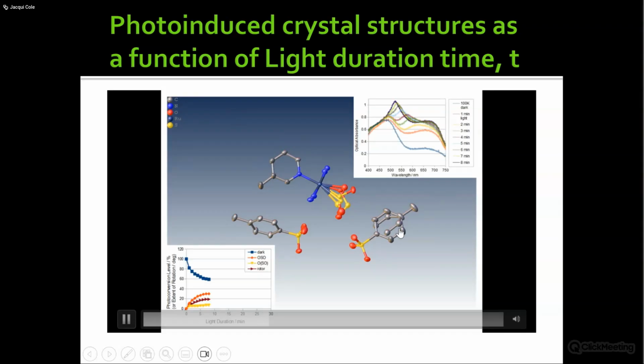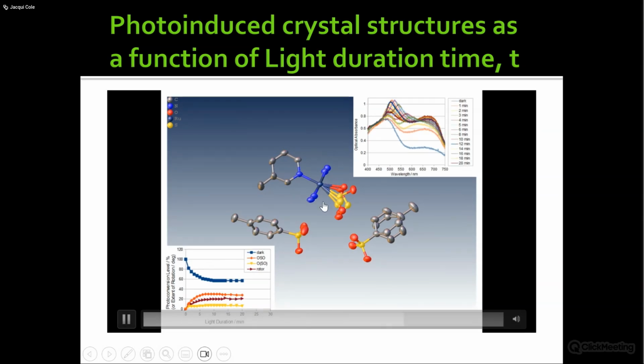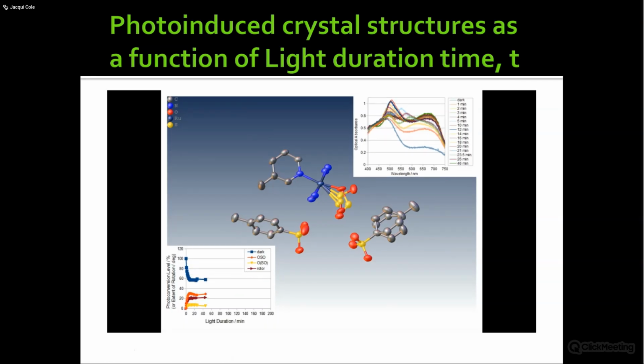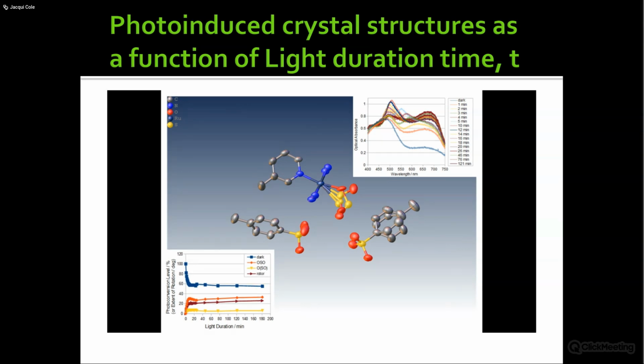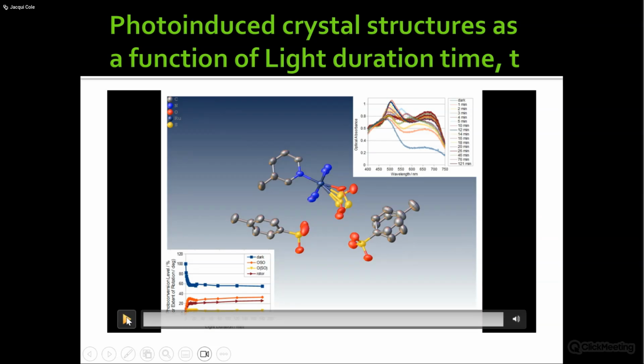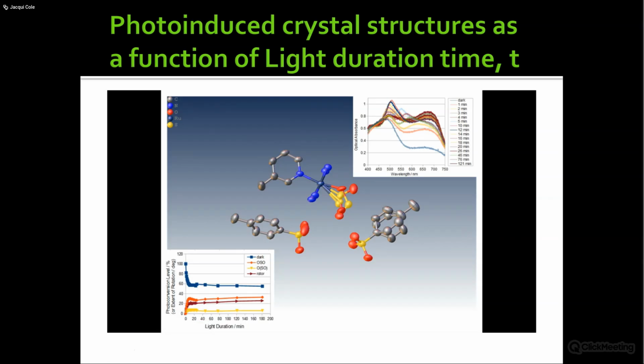So this is now us over a longer period of time, over 2 hours. And what you're seeing, I'll play it twice maybe, is the structures evolving as more of the photoisomer state is forming, and each of these clips, as you can see, is another crystal structure determination. So a whole crystal structure data collection at each jump. I think I'll play it again so we can talk it through in more detail. And on the top right, you're seeing the optical absorption spectroscopy change in step with the crystallography change, right? And then on the bottom left is what you've already seen.